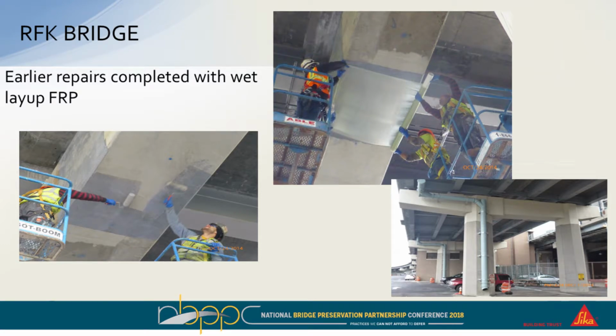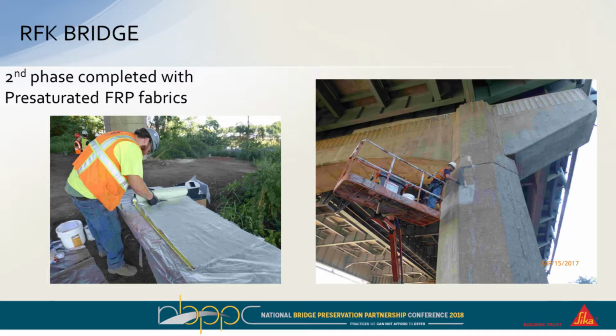So here you see, originally, the first phase of this project actually used the wet layup system. So here's an example of the concrete being primed. The fabric, which has already been saturated, is being laid up on the underside of the girders, and then finally it gets coated. So this was the first phase. The second phase was done with a new contractor where they actually utilized the pre-saturated systems.